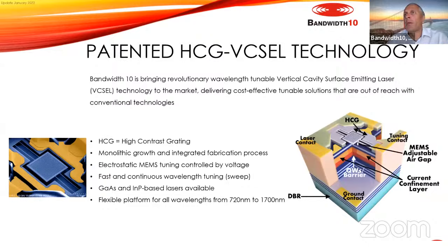What we have is basically based on a MEMS that is a grating on top of the VCSEL. It's called a high contrast grating. So it's a grating that can be moved down and can shorten the cavity. By shortening the cavity, so you apply a bias on the grating, the grating moves down due to the electrostatic effect, and you shorten the cavity. By doing this, you can directly modulate electrically the wavelength, and you can tune the laser.